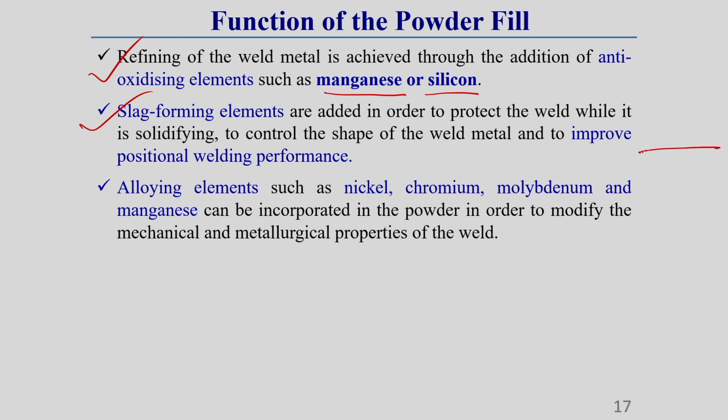as well as this weld pool. Over this weld pool there is a slag layer. As this slag layer covers this weld pool from atmospheric contamination, the chances of oxidation and other things are prevented. As well as this slag protects this weld pool, it also reduces the cooling rate. So, once the cooling rate is reduced, what happens is that your weld pool region undergoes an annealing type of effect. Due to the annealing effect, this weld material zone is comparatively more ductile than other exposed weld material. What I am telling, understand?